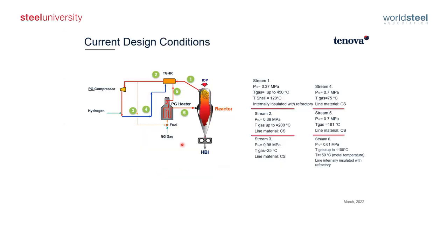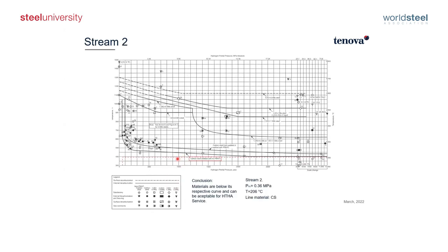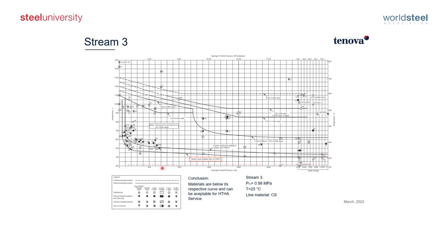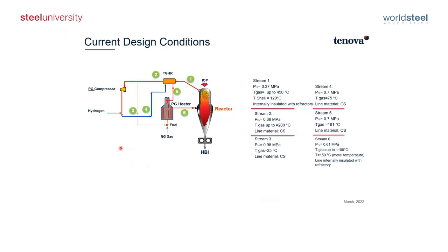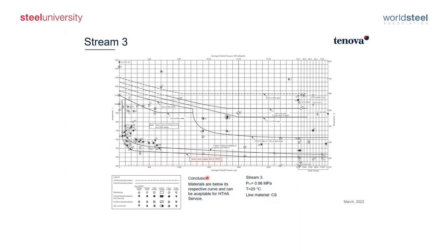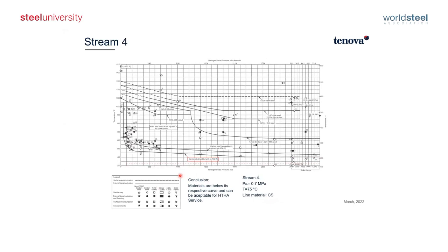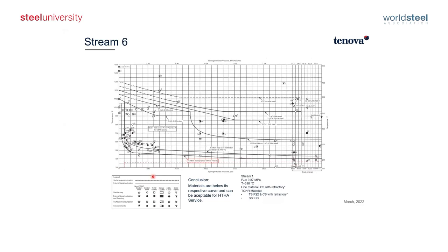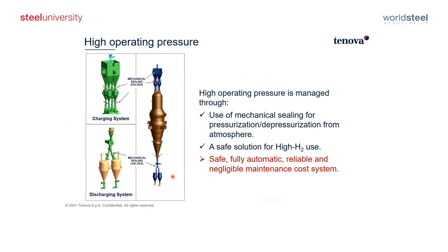Stream two is the stream outside of the recuperator, is even colder with a slightly higher temperature, but not much. Stream three is the feeding line, so no temperature at all. You see that the line is very low, and so on and so forth. You see that in all the areas, stream five, stream six, all, in all the critical areas where hydrogen is in touch with metallic parts, namely tubes and vessels, in the HTHA process, you never reach the critical condition.